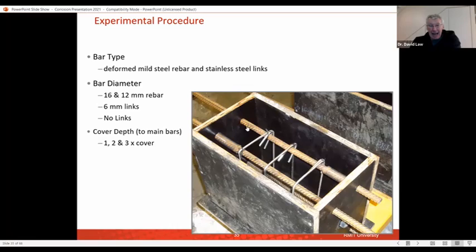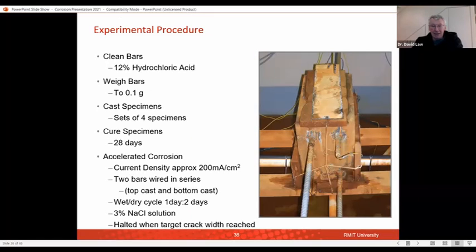And so we designed a set of specimens where we've got the bond in, we've got a bond breaker here, so when we clamp it down, it's not pressing on the bar. We will have 16 and 12 millimeter bars we looked at. We had stainless steel links to make sure these didn't corrode. We were just trying to corrode the bars. And we looked at a range of cover depths of 1, 2, and 3 times the cover of the bars over a large set of specimens that we've looked at.